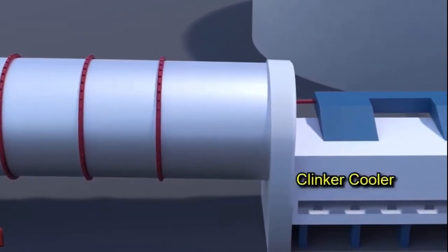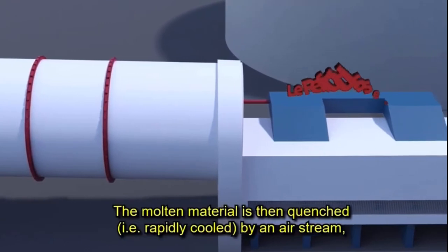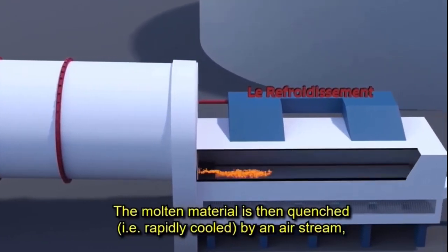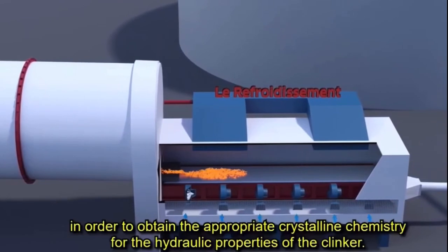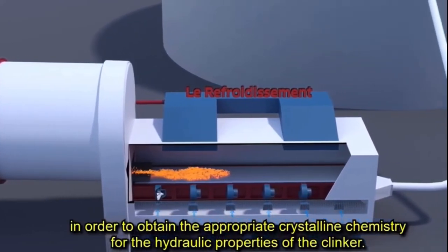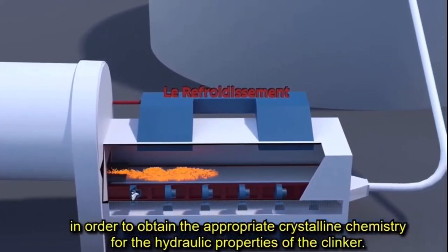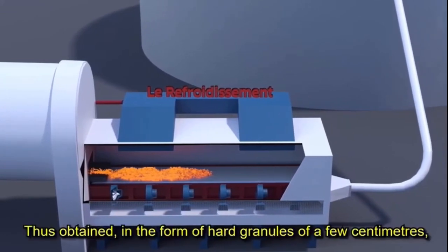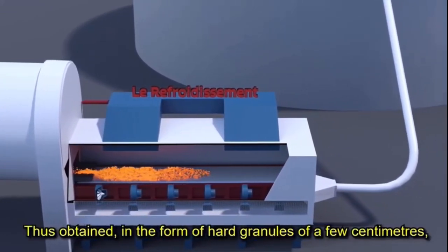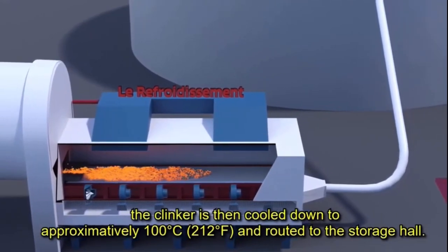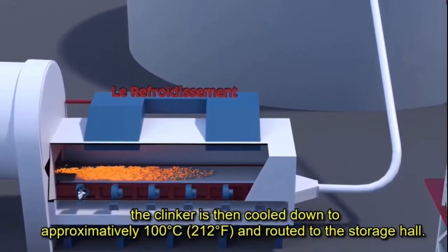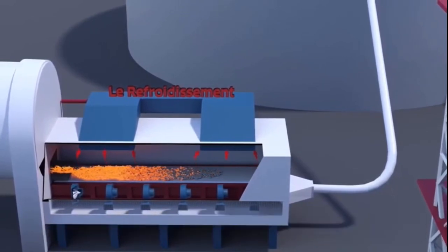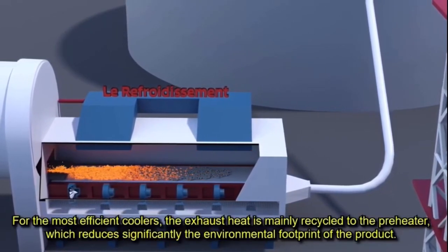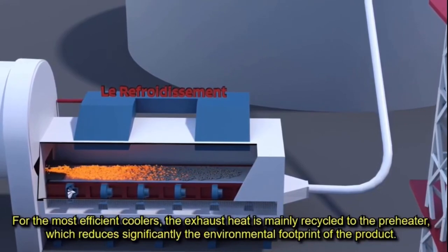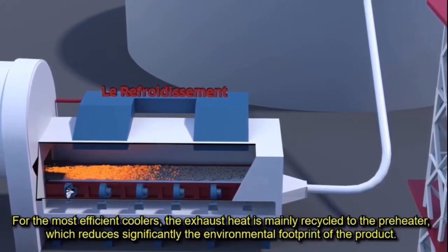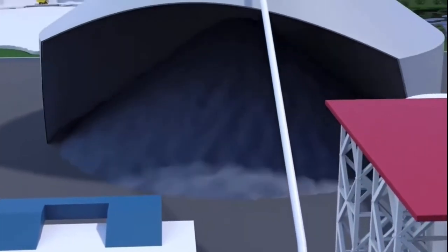Cooler. The molten material is then quenched, meaning rapidly cooled, by an airstream in order to obtain the appropriate crystalline chemistry for the hydraulic properties of the clinker. Thus obtained, in the form of hard granules of a few centimeters, the clinker is then cooled down to approximately 100 centigrade and routed to the clinker storage hall. For the most efficient coolers, the exhaust heat is mainly recycled to the preheater, which reduces significantly the environmental footprint of the product.